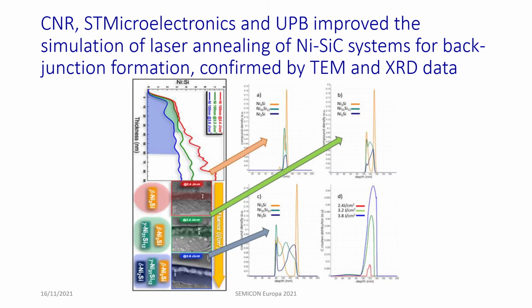A next example of a project result concerns the simulation of a laser annealing process, in this case targeted at back junction formation. A project result produced by CNR, STMicroelectronics and UPB. This simulation was validated using TEM and XRD data. And if you look at the comparison slides, you see a very good fit of the data to the model, showing that the simulations are quite good and can be used also to model this process.